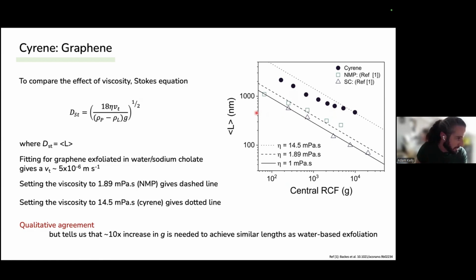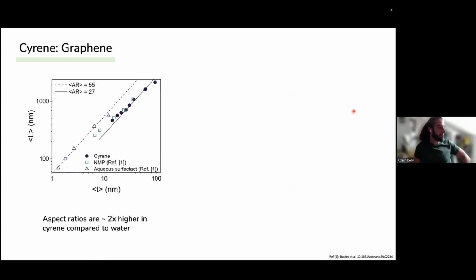So if we want a length of, for example, 500 nanometers that we have here in water, we need to use a 10 times higher G-force on the centrifuge in order to produce something of similar length. So further analysis here, we plot the length of the nanosheets versus the thickness for the aspect ratio. We find in water, we get an aspect ratio of about 55. And then with the higher viscosity solvents in cyrene, we get a much lower, almost a half. The aspect ratio is almost half that of that exfoliated.